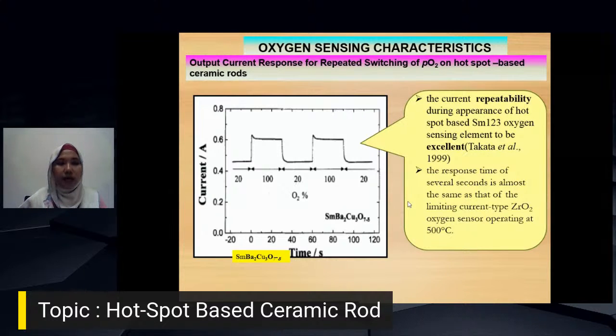when you change the concentration of the oxygen in the surrounding, the current passing through increases when the oxygen concentration changes from 20% to 100%. And in the case of changing oxygen concentration from 100% to 20%, the current passing through drops rapidly to the initial level, so the current repeatability for this type of ceramic rod oxygen sensing element is excellent.